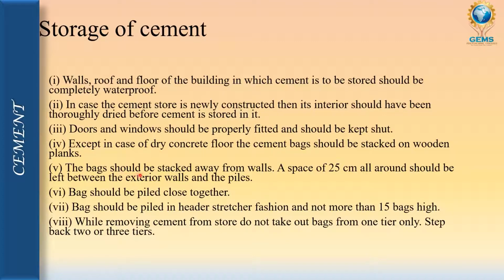The bags should always be stacked away from the wall. A space of 25 cm all around should be left between the exterior walls and the piles, because if they touch the wall or pillar, they can absorb moisture. So it should be kept 25 cm away. The bags should be piled closely together. If they are kept closely together, they will not absorb moisture.